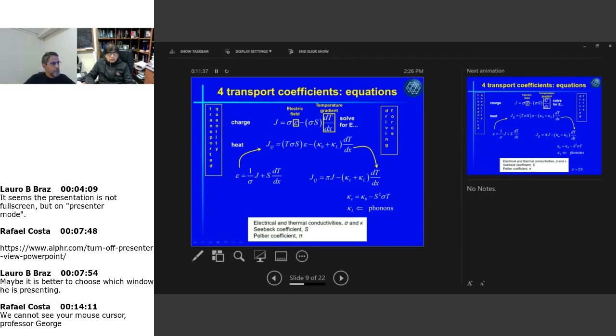So we have the electrical and the thermal conductivities, which are sigma and kappa, expressed here as the sum of kappa electrons and kappa lattice. The Seebeck coefficient, which is S, and Pi, which is the Peltier coefficient. And if you do this transformation that I showed here, Pi is simply T times S. This is the so-called Kelvin relation, and it can be proven using thermodynamical arguments. So it's a universal relation.